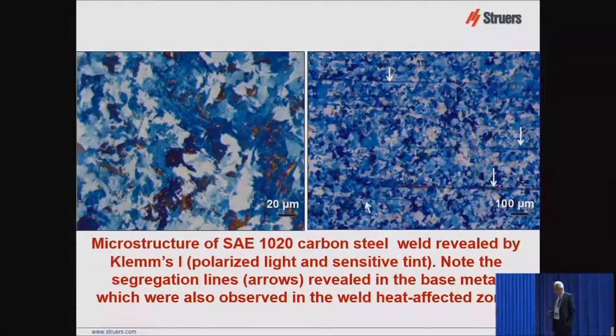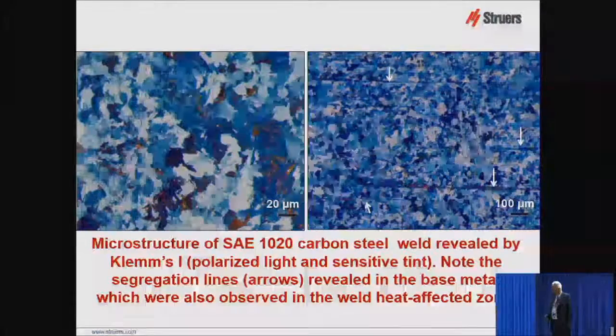And here's a couple color etchants for the weld metal and that area where you can see segregation in the heat affected zone. That shows up beautifully with color etching, but not always very well with Nital. On the left, this is 500X. On the right, this is 100X.